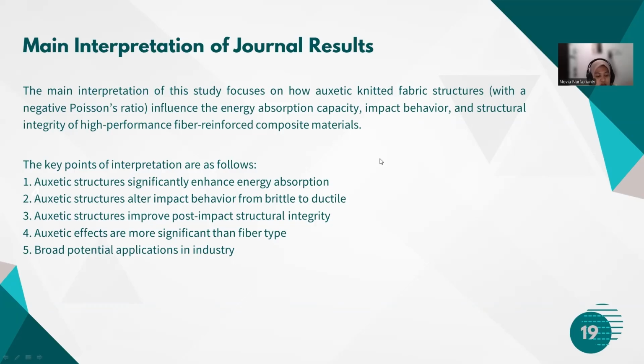This indicates that the effect of the structure's geometry has a highly significant influence on the mechanical properties of composites, even more dominant than the type of fiber used. The mechanism behind this improvement is due to the lateral deformation characteristic of auxetic materials, where the material expands laterally under tension, creating denser areas to absorb impact energy. And auxetic structures alter impact behavior from brittle to ductile.